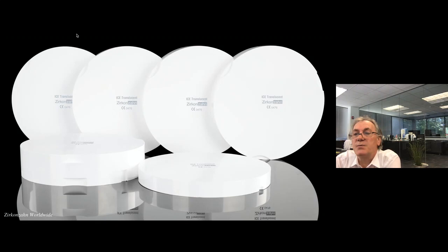So we have zirconia materials with different characteristics in relation to light absorption and that integrates to specific solutions or situations. The ice zirconia is ideal for creating substructures that require complete layerings. It is about 1,400 MPa in strength, therefore can be used for full arches as well as single copings.